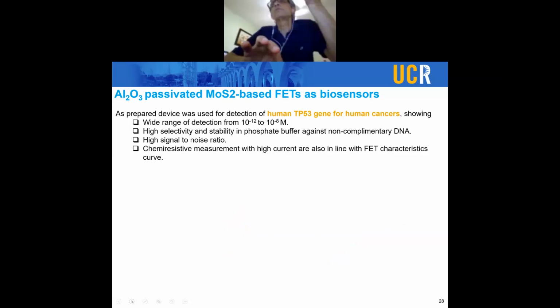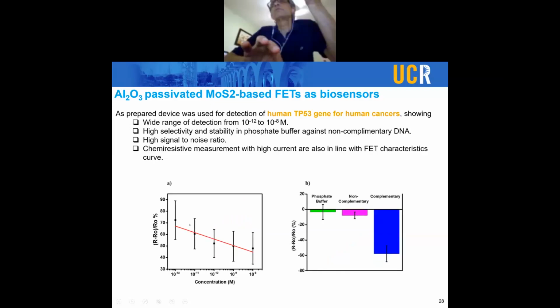And it is going to be easy to do on that. And it is a good sensor with a very good calibration, a very low, down to picomolar detection limit for DNA, good selectivity. It was highly selective for complementary, but not for non-complementary DNA, which has either 2 base mismatch or 3 base mismatches.